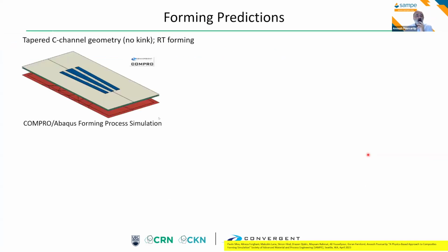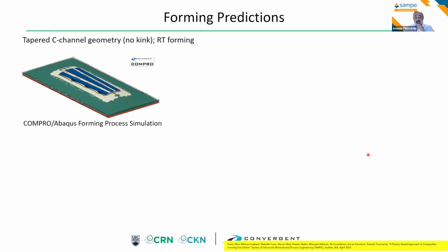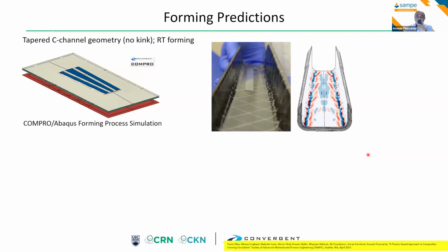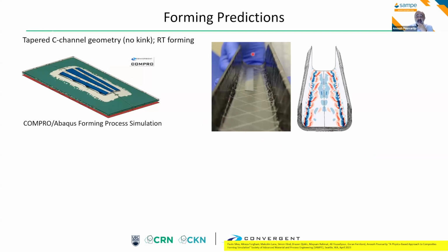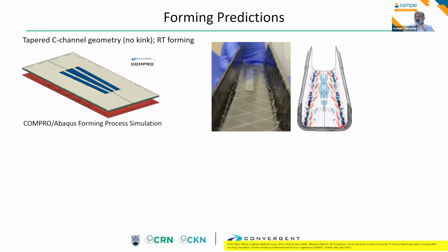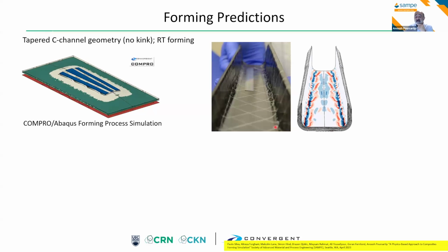edge. So here what we're doing is we're looking at a tapered C channel. This is a collaborative project that was done with the National Research Council of Canada. And as you're forming this, in this case, we're looking at an extreme example where it was formed at room temperature. You start to see wrinkling in the inside of the corner. And the way that one then looks at that in terms of prediction at the moment is to look at the strain fields and identify zones where the strain field is conducive to wrinkling.